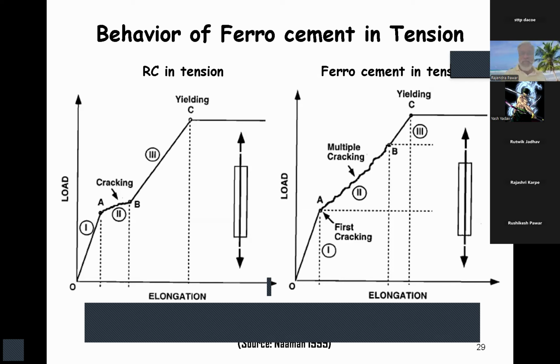Here in ferrocement, similarly up to point A, it's the first cracking. But beyond that, due to the steel reinforcement, the staggered reinforcement, the multiple cracking zone is there between A to B, which is elongated, more than the RCC. We can easily see that. The strength in this multiple cracking zone is used while designing the ferrocement components. And then the yielding point comes. So this is how the tensile strength as well as compressive strength is increased in ferrocement, only because of the even distribution of the steel reinforcement.